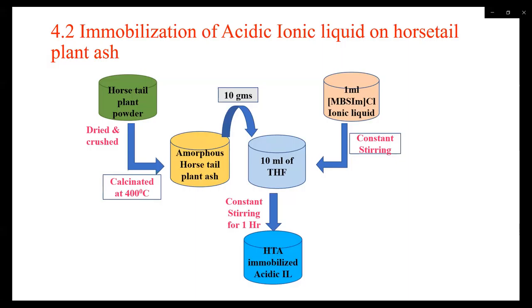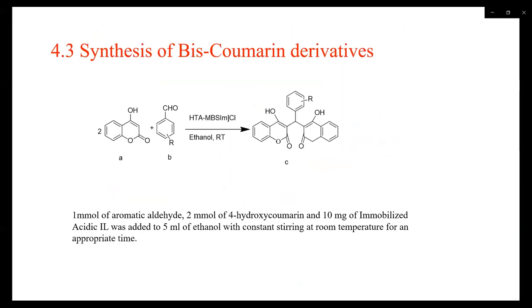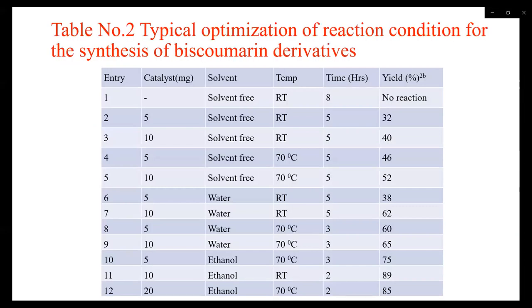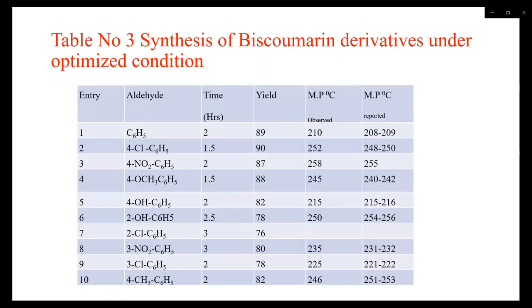We have used this dual acidic heterogeneous catalytic system for the synthesis of bis-coumarin derivative, where aromatic aldehyde reacts with 2 moles of 4-hydroxycoumarin, using ethanol as a solvent at room temperature. In order to check the optimization of reaction, we selected the reaction between benzaldehyde and 4-hydroxycoumarin and carried it out using different solvents, different temperatures and different concentrations. After selecting the optimized condition, that is the use of 10 mg of catalytic system using ethanol as a solvent at room temperature.